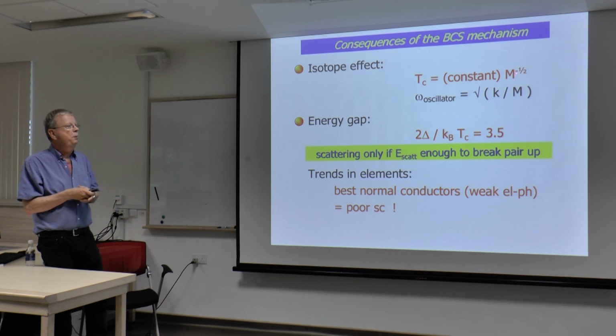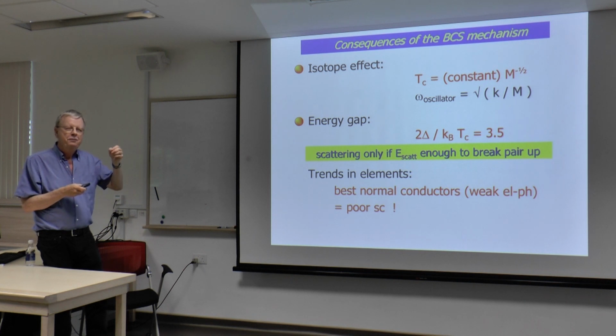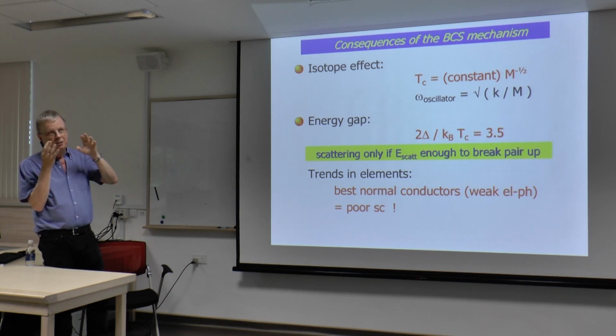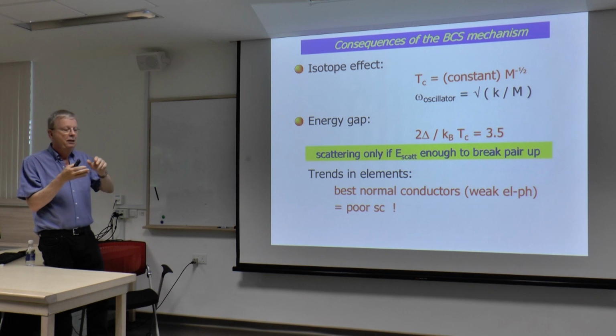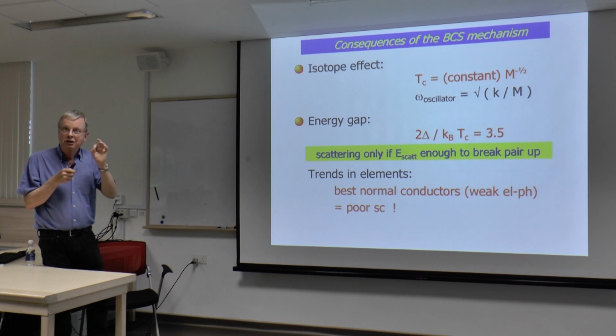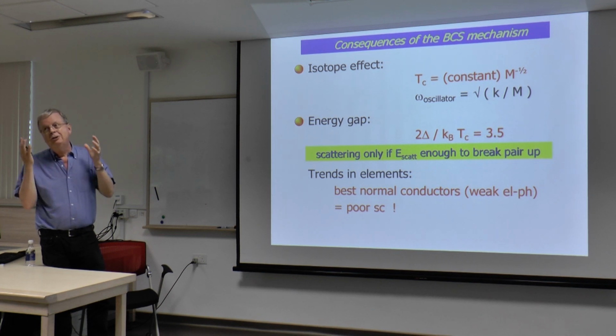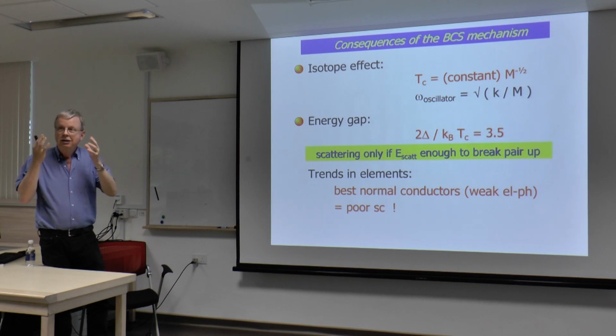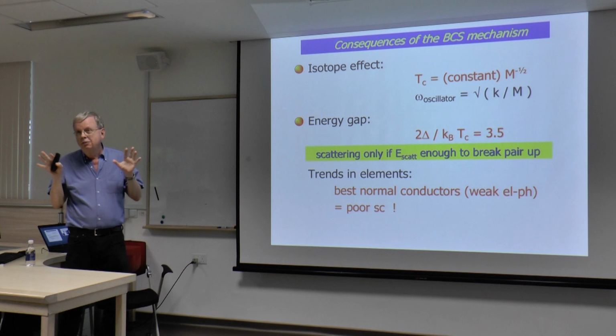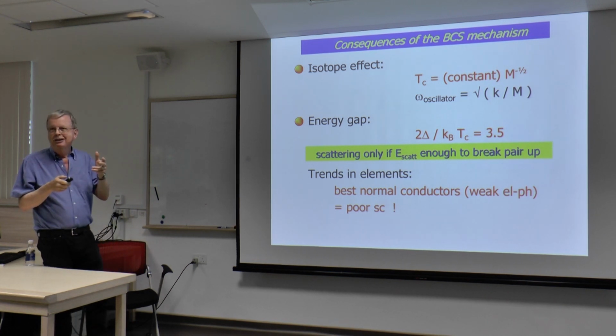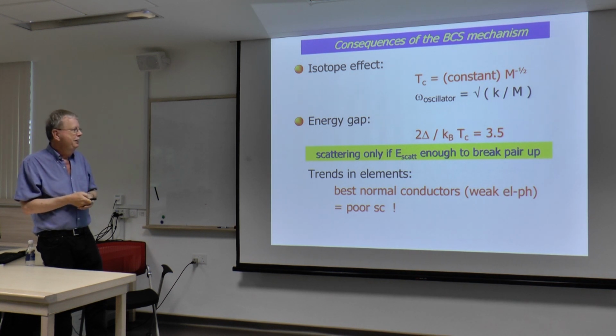It turns out in the high TC cuprates, the one that Bednorz and Mueller discovered, the lanthanum, they doped it with barium, it's now strontium that is used: lanthanum, strontium, copper, so 2 lanthanums, 1 copper, 4 oxygens. Dope a little bit of the lanthanum, we'll talk about that, with strontium or barium, and you get superconductivity. It turns out that has an isotope effect. If it has an isotope effect, there's electron-phonon coupling. If it doesn't have an isotope effect, remember it could be ruthenium, right? It still could be BCS. So isotope effect, yes, it's conventional. Isotope effect, no, you're not sure. You gotta be a little careful. But just walk down the hall to Phil Anderson and ask him, if you can find Phil down the hall.